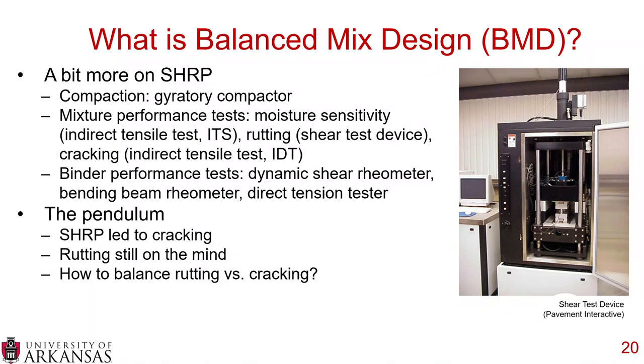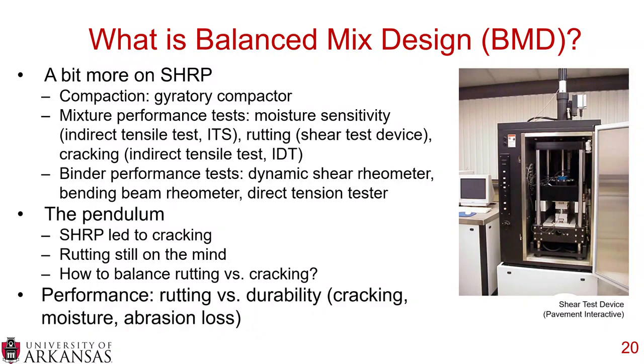And the problem is that the pendulum was SHRP, it led to cracking, but rutting was still on people's mind. So we implemented SHRP in the United States. We now have a cracking problem, but people are afraid to just throw a ton of asphalt in it or, you know, change that Ndesign level kind of arbitrarily, because people are a little nervous about that pendulum swinging back the other direction, and then we have a rutting problem. So it comes down to how do we balance rutting versus cracking? And this is where the term balanced mix design comes from.